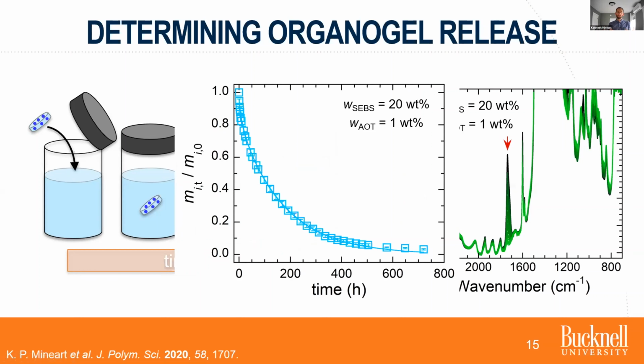In our case, because we're looking at things in terms of the gel, whereas others have traditionally looked at the surrounding solution, we're looking at what we refer to as the retained mass of AOT in the gel. And so initially you have 100% AOT in the gel, and you see it going down over time as we approach roughly 0 as all of the AOT is being released.